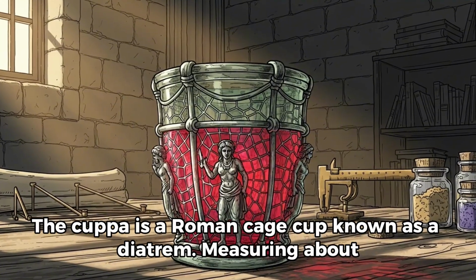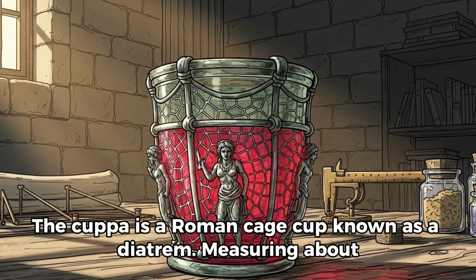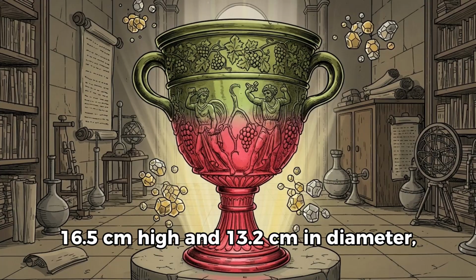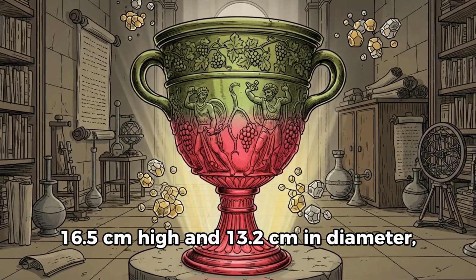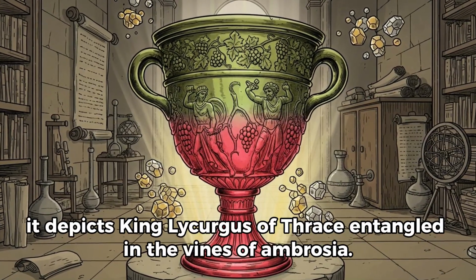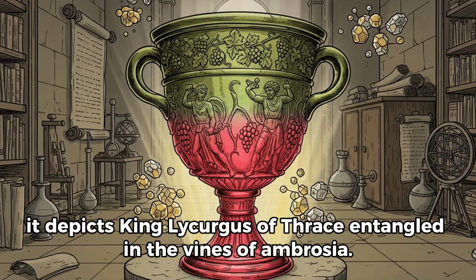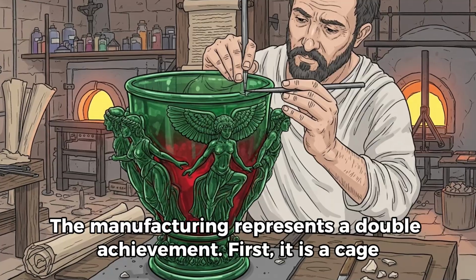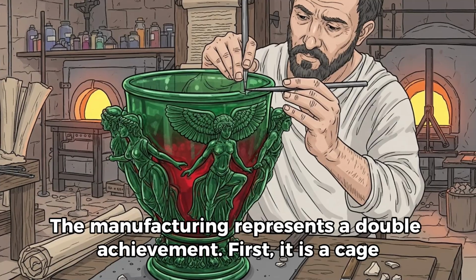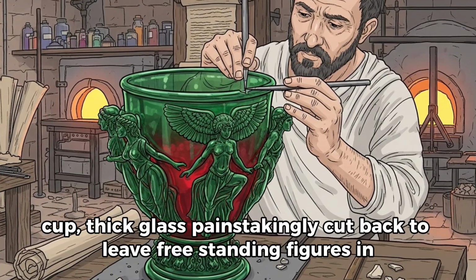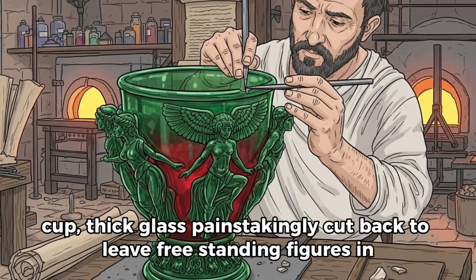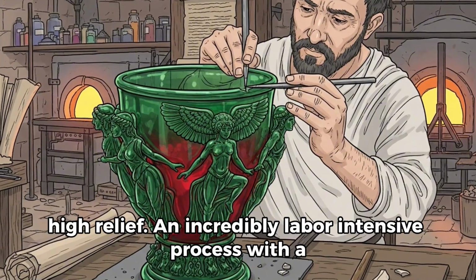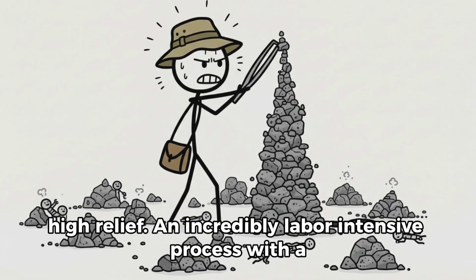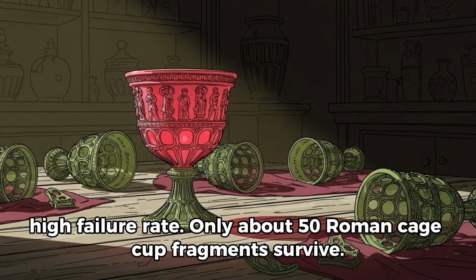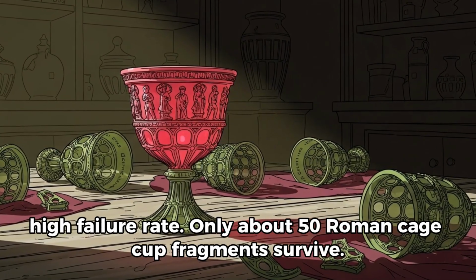The cup is a Roman cage cup, known as a diatretum, measuring about 16.5 centimeters high and 13.2 centimeters in diameter. It depicts King Lycurgus of Thrace entangled in the vines of ambrosia. The manufacturing represents a double achievement. First, it is a cage cup, thick glass painstakingly cut back to leave freestanding figures in high relief. An incredibly labor-intensive process with a high failure rate. Only about 50 Roman cage cup fragments survive.